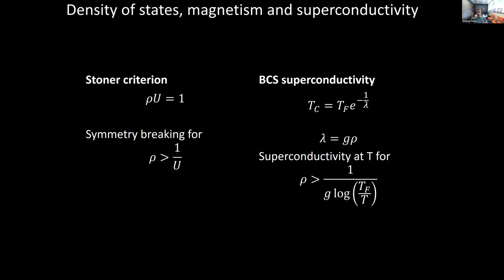And this turns out to be the useful knob because high density of states is the harbinger of correlated electron behavior. The reason for that is that at a single particle level, when you have a high density of states, it means that there's essentially a large quasi-degeneracy between different states. If you have some finite density of electrons within, let's say, some Van Hove singularity or some other situation where the density of states becomes very large, then there's a large quasi-degeneracy, and that means that correlation energy scales can become important. And you can see this already in very old types of physics where correlated states emerge, in particular magnetism and superconductivity.